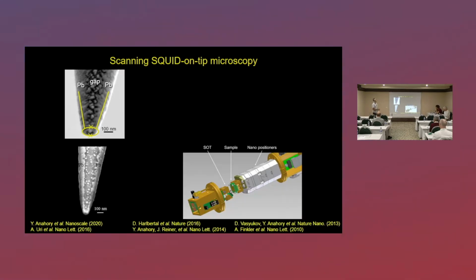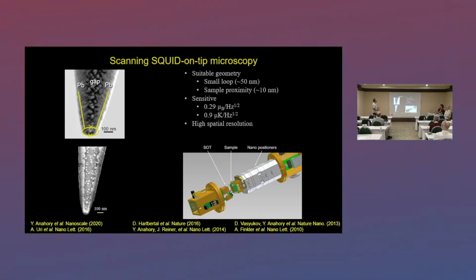And the idea is to strap this to a scanning probe microscope and to do magnetic and thermal imaging at a nanoscale. So just quickly, the features: it has a suitable geometry. Why? Because it has a very small loop, and we can get this loop very close to the sample. As a result, it is extremely sensitive. We're talking about sensitivity to a magnetic moment that is smaller than 1/3 of the spin of an electron. Or if you're talking about thermal sensitivity, which I will not talk about in this talk, the sensitivity is better than 1/1,000,000th of a degree at 4.2 Kelvin. And all this with a high spatial resolution, and we can work at a relatively high field, which is not the case for other scanning SQUID techniques.